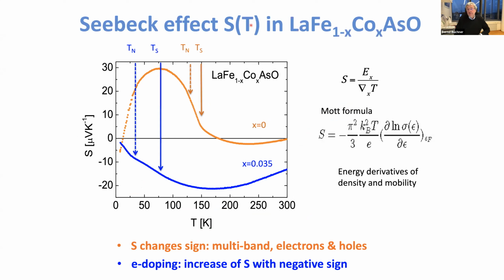The Seebeck effect, what do we measure here? It's not scattering. So it's really a different quantity than the resistivity. What you measure here, if you, for example, take this easy Mott formula, is the energy derivative of the conductivity. So energy derivatives of density and mobility. And it's of course well known that it's very, very sensitive to details of the Fermi surface. If you have the parent compound at x equal to 0, so you have basically undoped compounds, holes and electrons with the same amount. Therefore, you have this crossing of the sign close to 0. If you electron dope the system, it becomes negative.